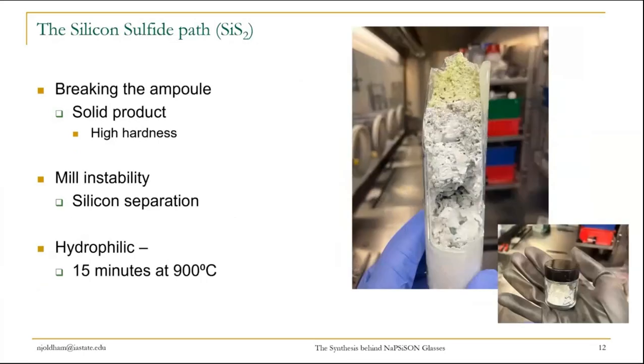Once we've distilled off the sulfur, we can then have this ampule brought into the glove box and broken in half. This product is actually very solid and very hard, so in trying to work with it, you have to use a chisel and a hammer to get the exact quantity you need for the certain composition you want. It is unfortunately unstable in a SPEX mill, something where you have a steel ball mill, because the steel balls will actually separate the silicon away from the sulfur in the silicon sulfide bonds and ruin the purity of the sample. It's also hydrophilic, which means that we have to calcine it again right before adding it to our glass system.